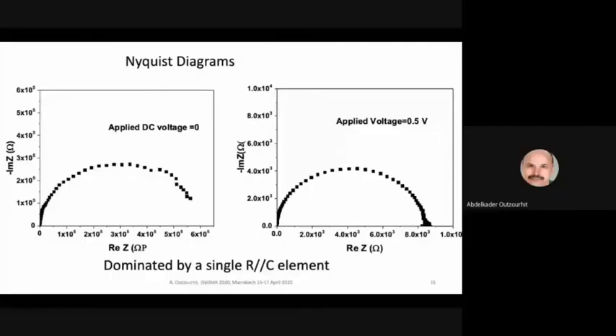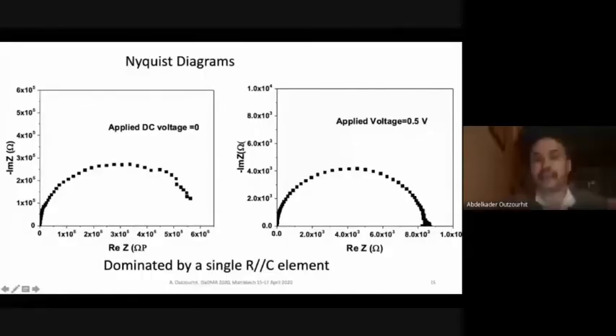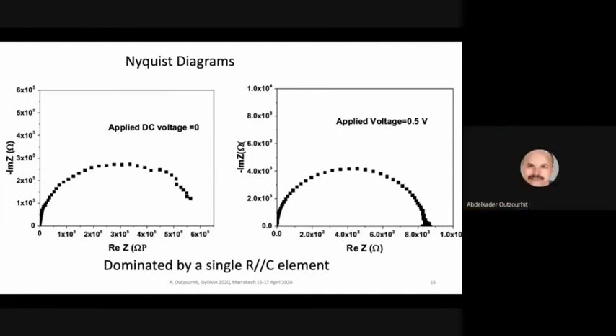And as you can see, this resistance here, which is given by the diameter of the circle, varies with the applied voltage. Okay, so it decreased, in fact, with the applied forward bias. It decreased from about 600 kilo ohms, or 0.6 mega ohms, to about 8 kilo ohms here. This is due to the fact that we forward bias this junction, reducing, in fact, its resistance, and also the capacitance, as we can see in the previous curves, will increase in the forward bias.